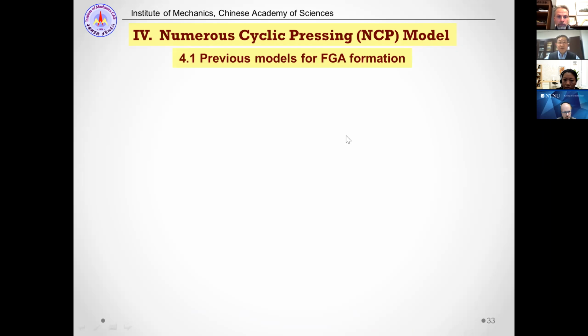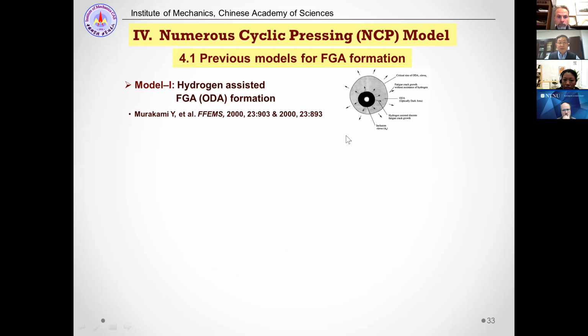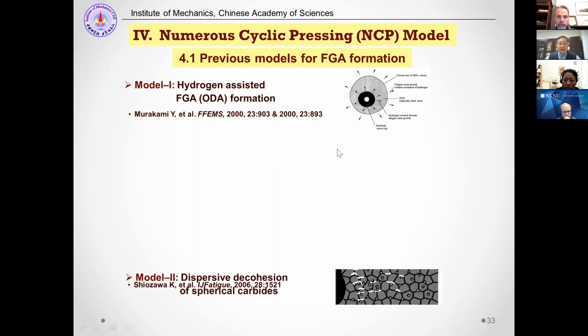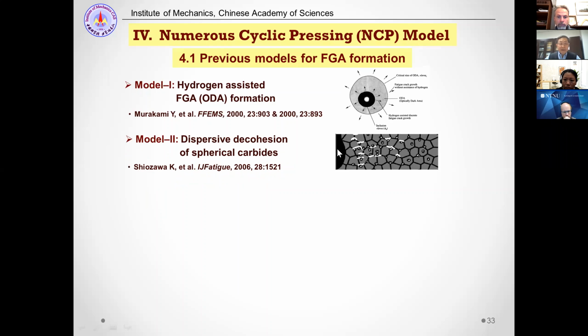First, I would like to mention some previous models. The first one is hydrogen-assisted FGA formation, meaning that the existence of hydrogen will cause the rough fracture surface at crack initiation. And the second one is called dispersive decohesion of spherical carbides, meaning that the existence of carbides will be the crack initiation point. That is the decohesion between the carbides and the matrix to form a rough surface at crack initiation.